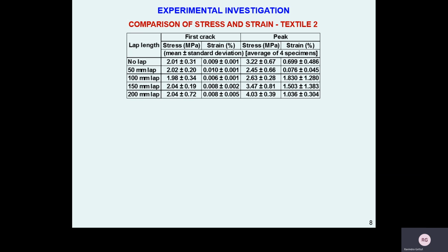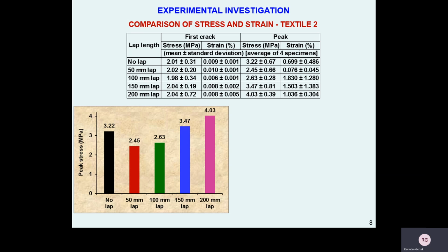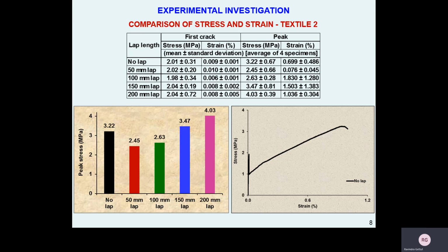The results for the second type of textile made of AR glass are here. The bar chart shows that there is not much improvement between the 50 and 100 millimeters of laps, and the performance is better with 150 and 200 millimeters of laps. This is portrayed in the stress strain behavior as well, where there is an improvement with increased length of splicing.